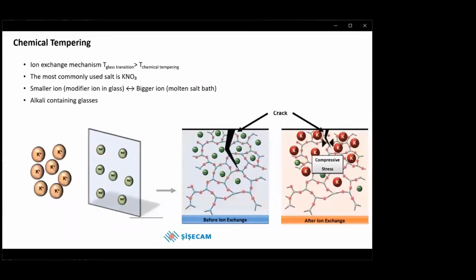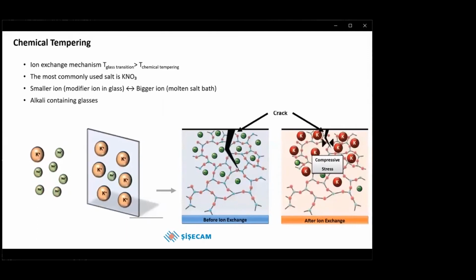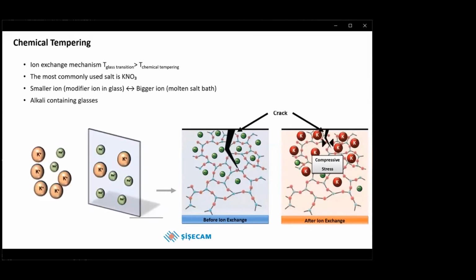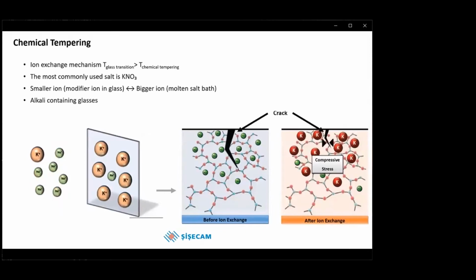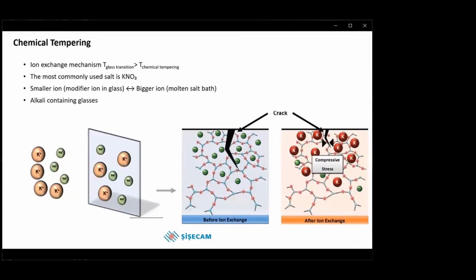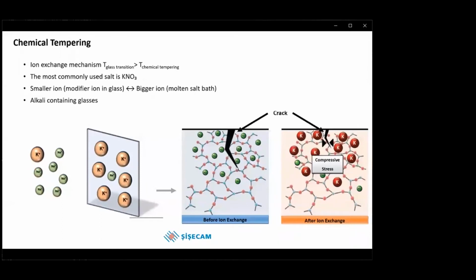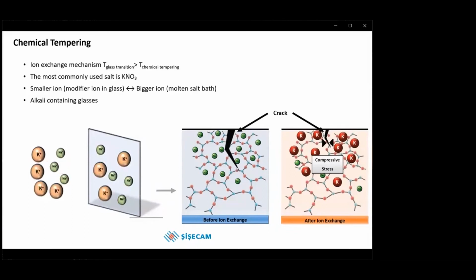Let's start with the chemical tempering process. The process needs relatively high temperature. It's performed below the glass transition temperature. Potassium nitrate is the most widely used salt in this process. It's an ion exchange process, an exchange of smaller alkali ions like sodium in the glass matrix with larger alkali ions like potassium in the molten salt bath. Ion exchange is realized in alkali-containing glasses. By this ion exchange reaction, a compression layer is formed on the surface, thus the glass is strengthened.